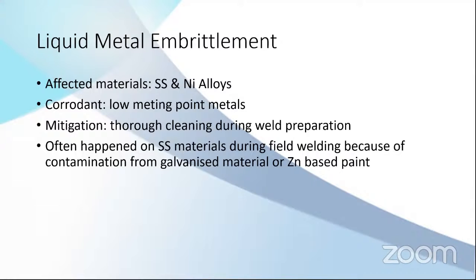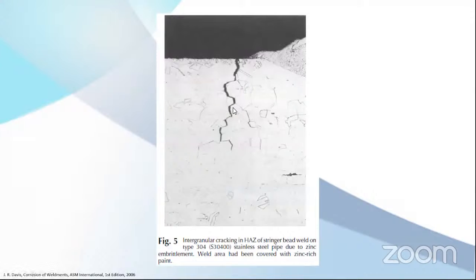It most often happens in field welding. Sometimes the stainless steel is in contact with galvanized material or with painted carbon steel. Normally painted carbon steel has zinc content in the paint. So when it has contact and leaves a residue on the joint, then when you weld the stainless steel, the zinc is melted as well, and the melted zinc attacks the grain boundaries. So this is almost always intergranular cracking. The liquid metal goes between the grains, and when cooled, it creates very high stress on the grains, and then it cracks. So this damage mechanism is not by the fluid, not by the surface, but by the contaminants.